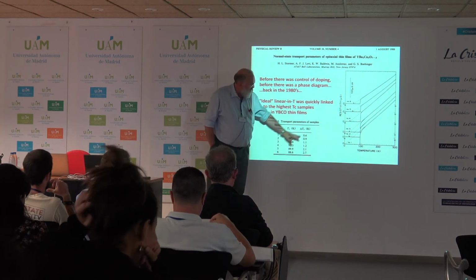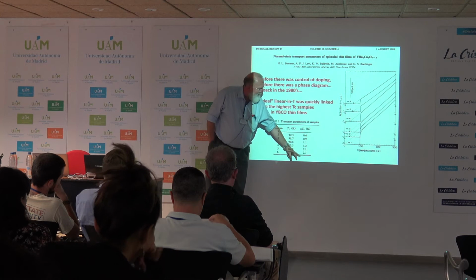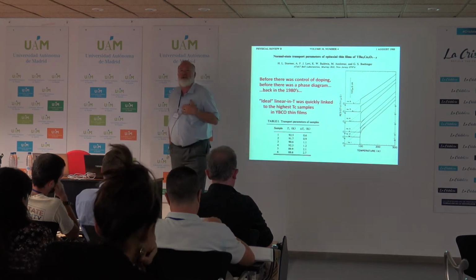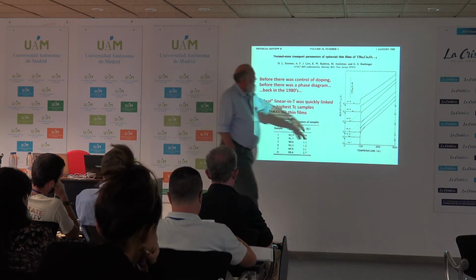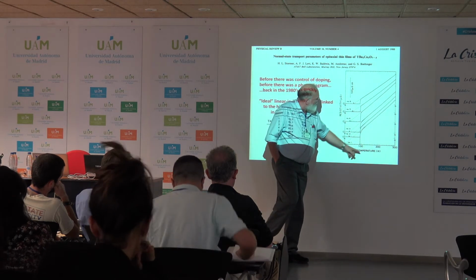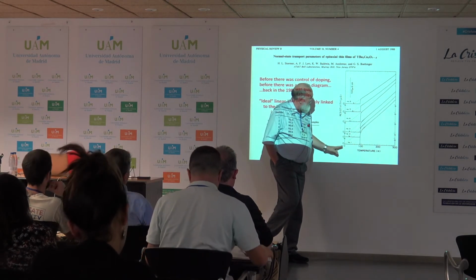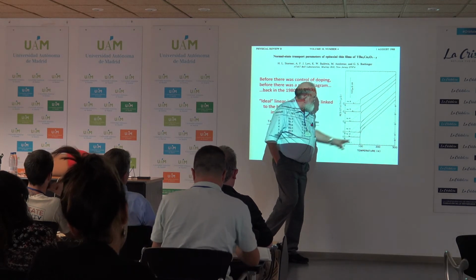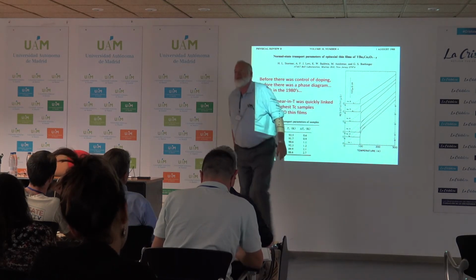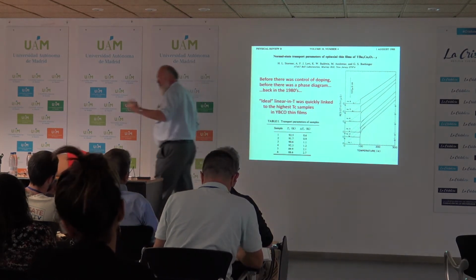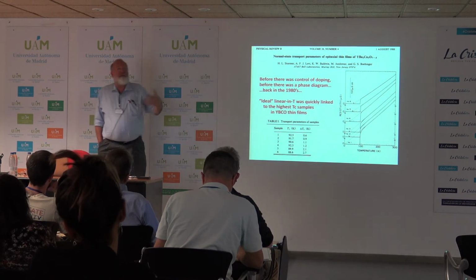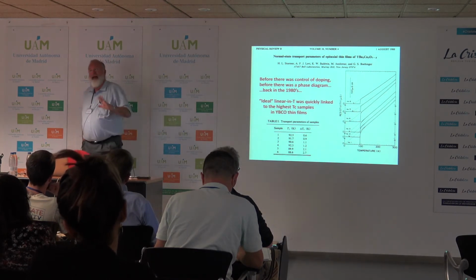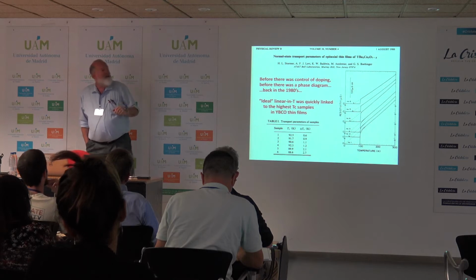They had no control over doping, but they were characterizing the quality of the samples by the sharpness of the transition. And in organizing the samples like this, the narrowest transition, which was also the highest TC, had a linear resistivity that extrapolated back to the origin. And still today, that's sort of the signature of the best behavior of a cuprate. Whether that's the right physical interpretation or not isn't clear.